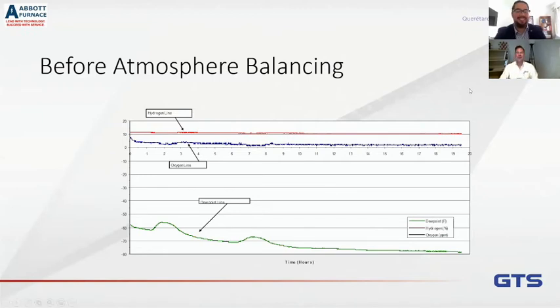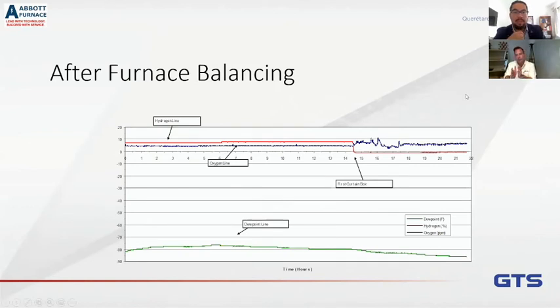Right. Okay. Now, if we go back in and we balance that furnace, look at this. Look at how this is where we're introducing that hydrogen. Notice how we introduce it and it goes forward, and we have that 8-9% going all the way forward. But going towards the back, it drops down to next to nothing. Now we're not putting hydrogen up the stack and wasting it. We're putting it where it needs to be. And you can see we still have a controllable oxygen level. It jumps a little bit in the back, but it's staying below 10 parts per million. It's not an issue. So everything's in control, but you've optimized your costs.